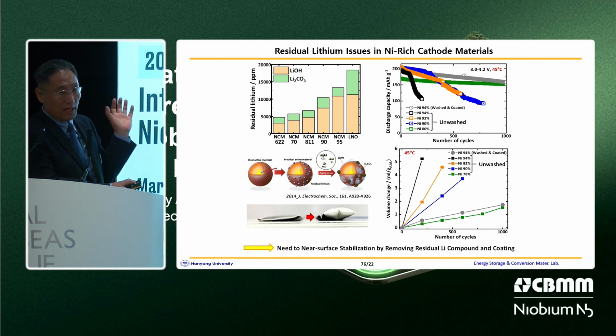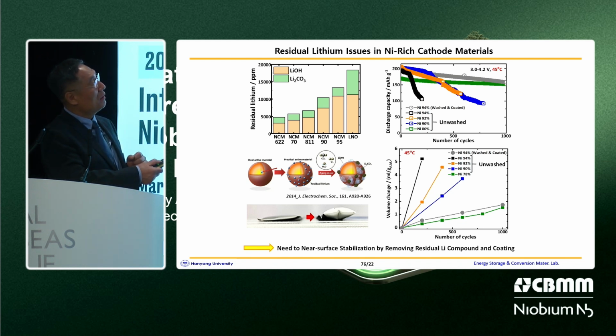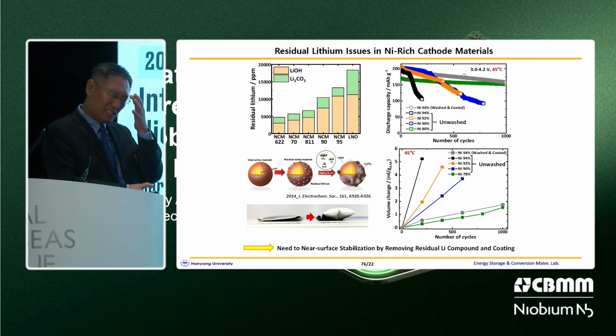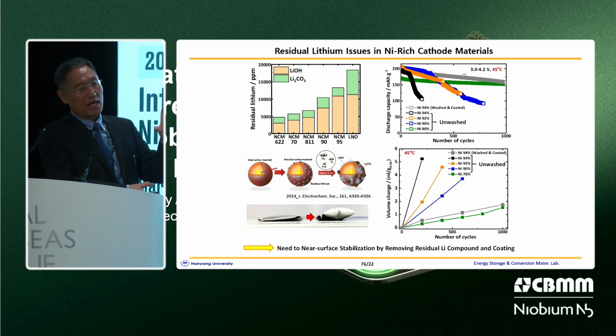As explained before, the residual lithium issue is less pronounced in small cells with lower loading levels. But when the loading level increases, or the cell is cycled at elevated temperature, the problem is pronounced.